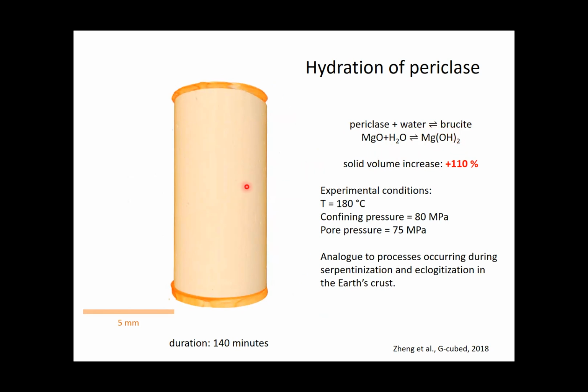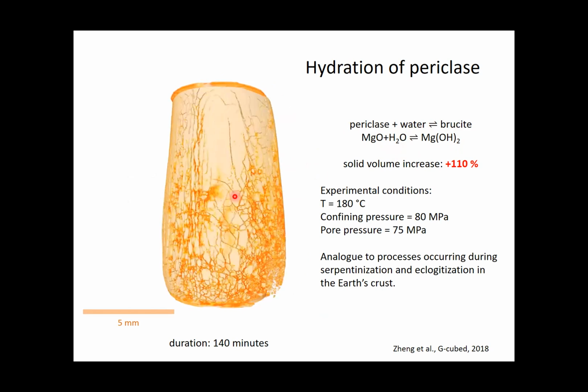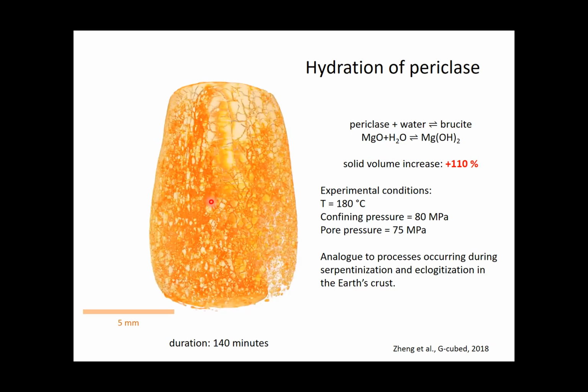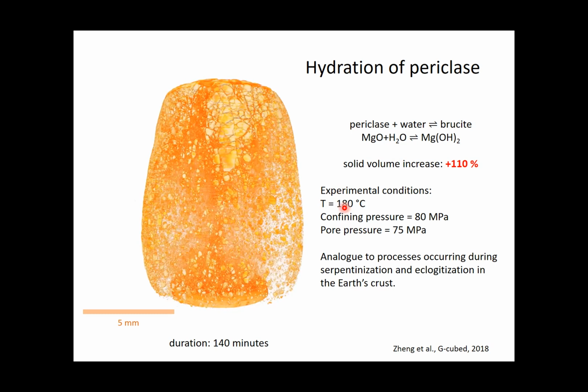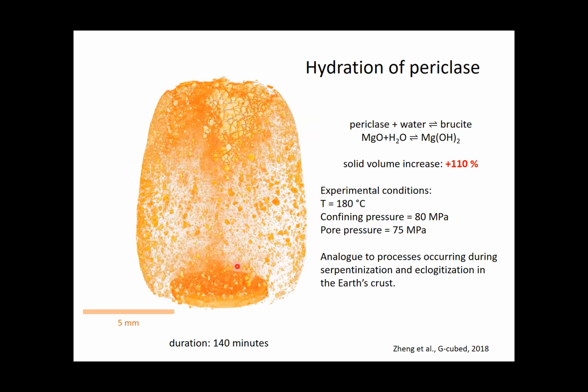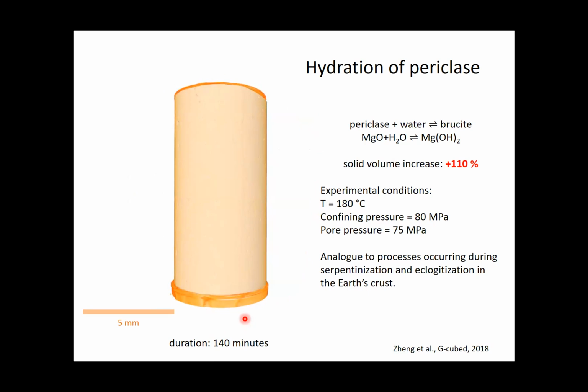I put it transparent, so we can see the fragments of the original material starting to be fragmented and spread around. So the brucite would be between these grains. Experimental conditions: it was below 200 degrees with a confining pressure and a pore pressure applied on this sample. The duration of this process is 140 minutes, and each 3D scan is made in a synchrotron inside this apparatus I mentioned before. Each scan takes between 2 and 3 minutes.